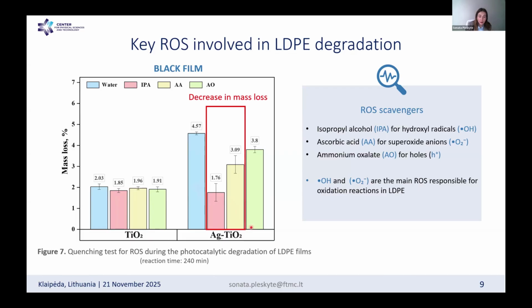And what was also interesting over here is that we noticed that, of course, the composite containing silver and titanium dioxide had a higher photocatalytic activity and showed better degradation efficiency for both black and transparent LDPE films. And this is most likely related to silver, which in this reaction system can increase the charge separation, as well as reduce the recombination rate between electrons and holes. So that was also interesting to check ourselves. Therefore, in this reaction system, we can see that the contribution of hydroxyl radicals is the highest, but the contribution of the superoxide radical is also very important, which is marked here in yellow color.